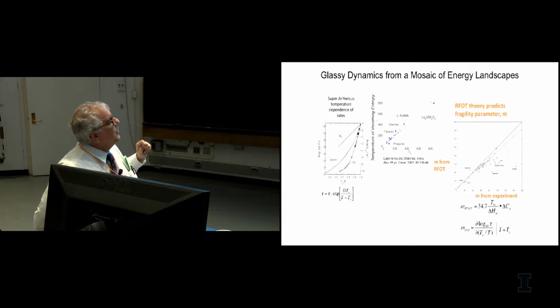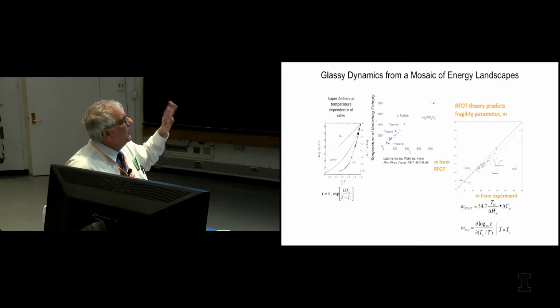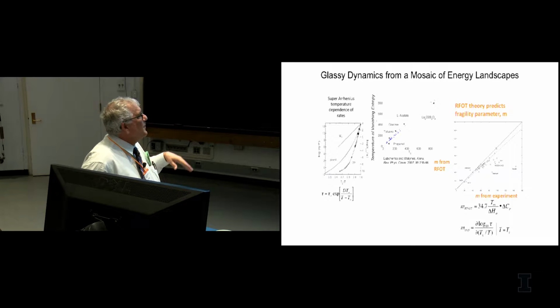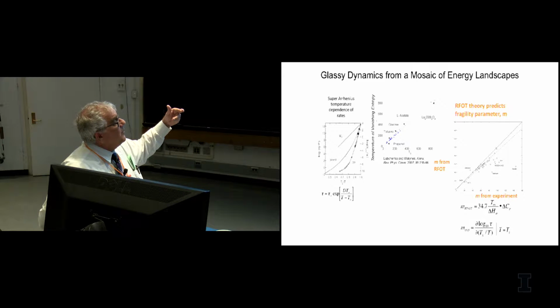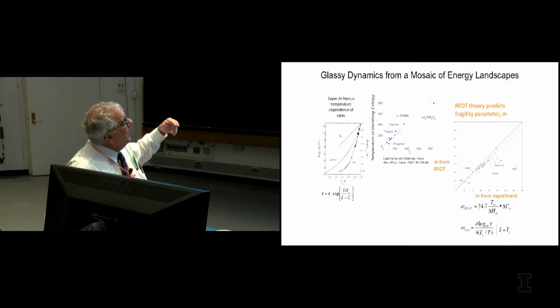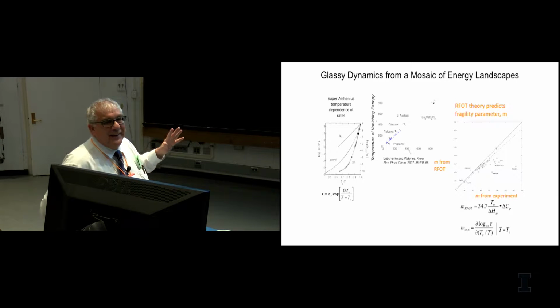This theory, the random first-order transition theory, predicts that it's a very simple formula, something like 35 times delta Cp. It's a delta Cp per particle, so things are not always made of simple spherical particles, so you have to normalize this by the entropy change on melting in order to see what it is per particle. This is the comparison of the theory and the experiment. There's no adjustable parameter in that graph. That's the line of slope 1. Now, maybe that comes from good living, but I would say that's a very strong prediction.